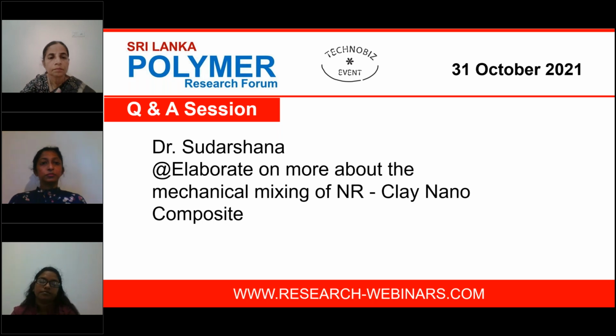But if we add the clay into latex and then coagulate it, the clay stacked with a few clay layers can be dispersed in the rubber. So mechanical mixing at that time is a little bit difficult. Once you add the clay into rubber, with a few clay layers, 10 or 20 in the stack, and you use mechanical mixing, the clay particle is already in the rubber, so it is very difficult to separate by friction.